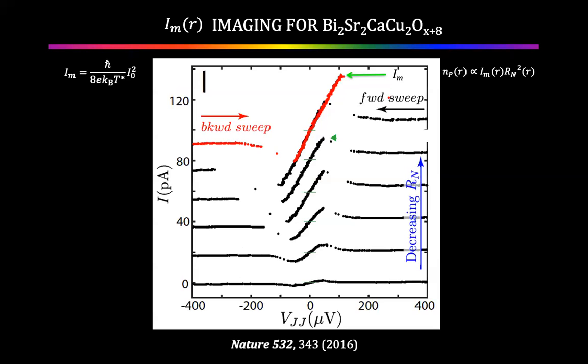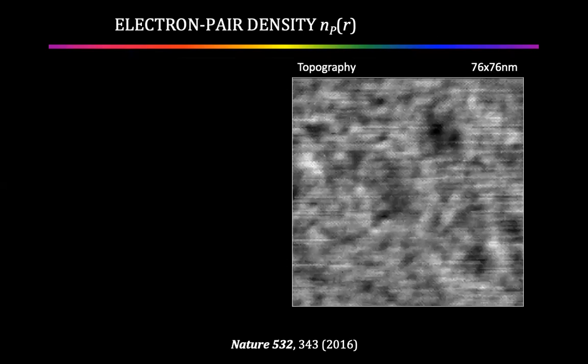Under those circumstances, if you push the junction resistance steadily into the range of mega ohms, then you see the Josephson branch appear. And you see here, these are only microvolts. There's no quasiparticles going through the junction here. It's only pairs, because we're only applying microvolts, even though we're getting a big current. So now what we're supposed to measure is the maximum in that current as a function of location. So in this field of view, this was Mohammed Hamidian's great work.